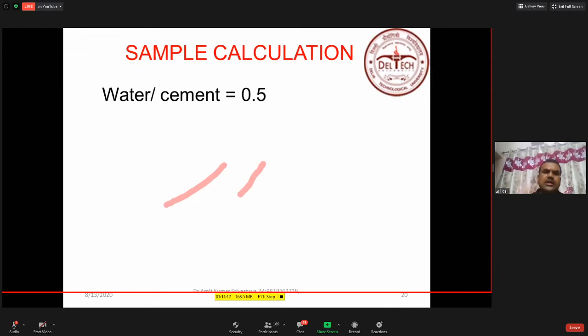And you will know that, suppose I'm considering taking the water cement ratio of 0.5, and you will be surprised to know that almost the water requirement for a given slump is the same, either you are using M25 grade of concrete or you are using M100 grade of concrete. The water is same. And by keeping the water constant, by varying the cement, I am getting a different water cement ratio, and by reducing the water cement ratio, I'm getting the higher strength. So that is the concept.